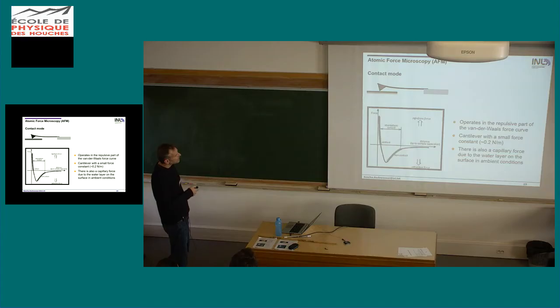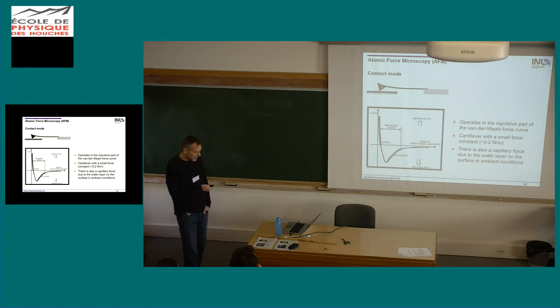So again, in atomic force microscopy, you can measure in contact mode, which means you just press your tip to the surface and then you scan it and you watch how this cantilever moves. And this means you're working in this part of the force distance curve. For this, you use small force constant cantilevers, so you want to use a soft cantilever, not to scratch your sample actually. You want to just feel how it looks, right? Sometimes there are capillary forces, so if you do this in air, depending on how high your humidity is, you have some water layer on your surface, and this leads to capillary forces that might have to be taken into account for the experiment.